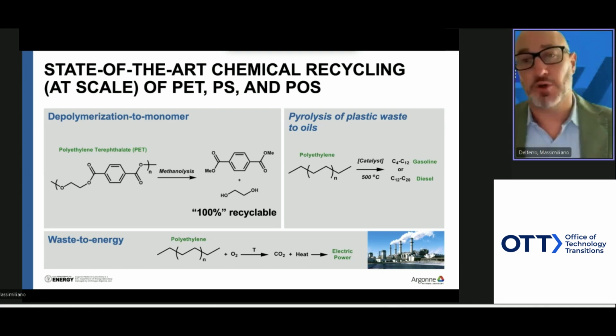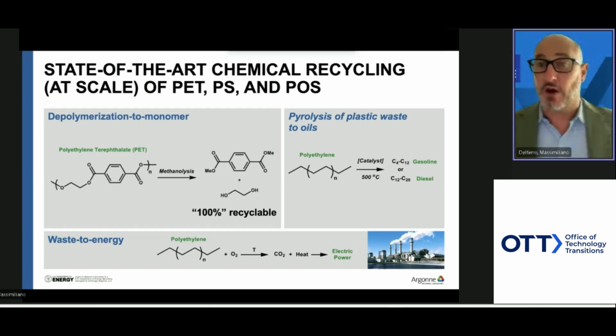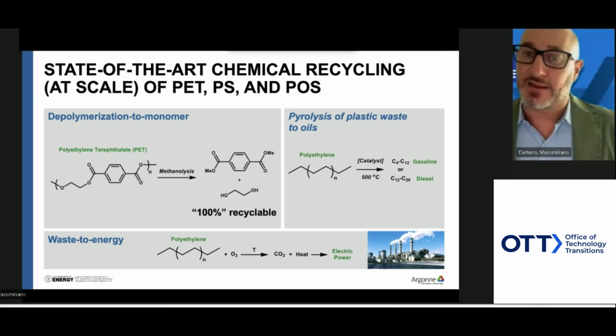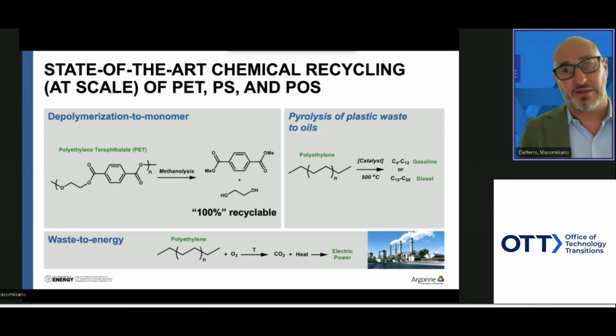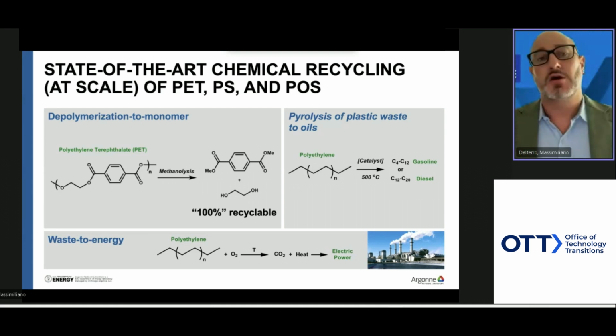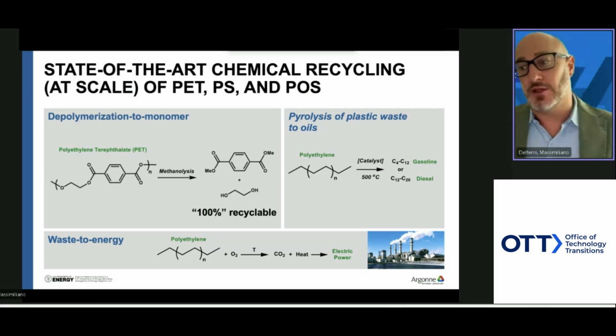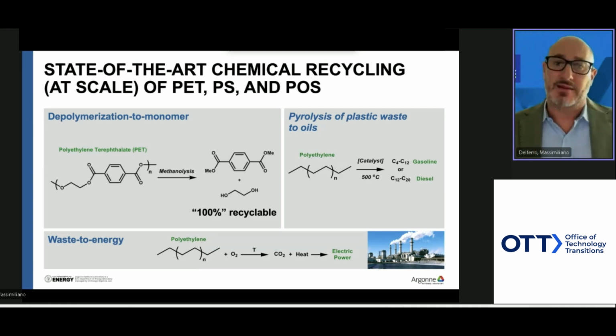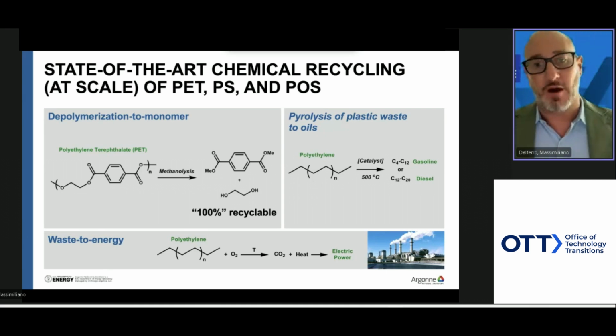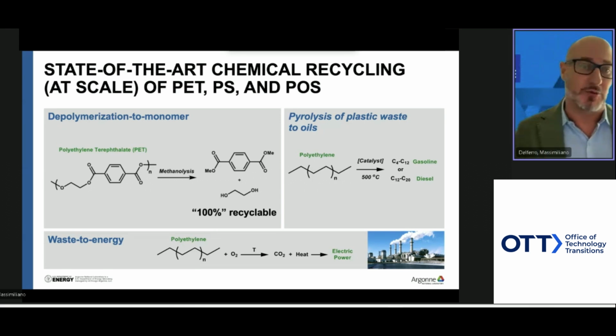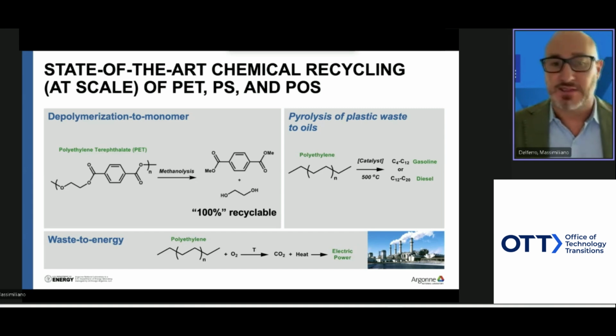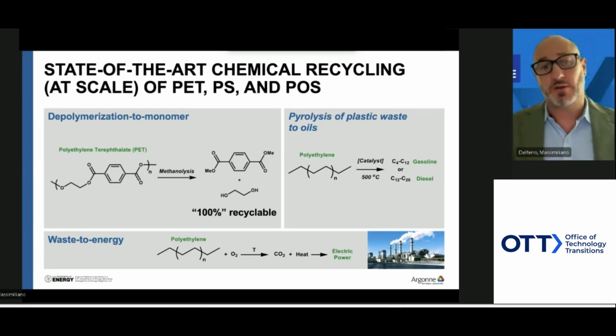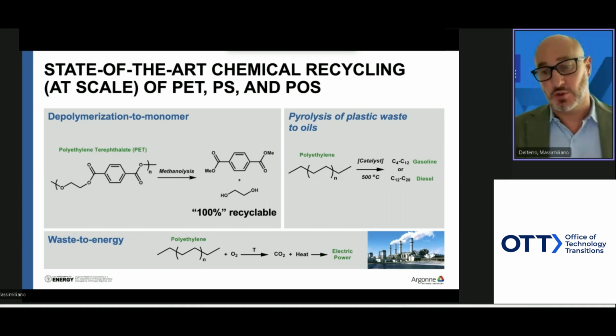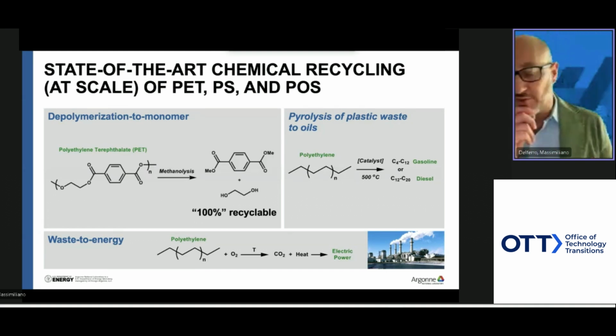Another technology that has been pushed a lot recently is the pyrolysis of plastic waste to oils. This is an unselective reaction, heating the polyethylene or the plastic at high temperature without oxygen to produce a distribution of products: solid, liquid, and gases. The gases can be recovered and used, for example, to heat the plant, and the liquid can be blended with existing oil and refined to make olefins that can be repolymerized to make, for example, polyethylene. There are also examples where the plastic waste is incinerated to produce heat and then electric power. Clearly, the downside is producing CO2 as a byproduct. This is what we are doing so far.